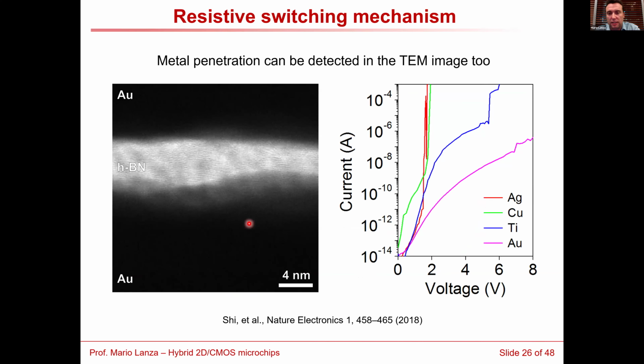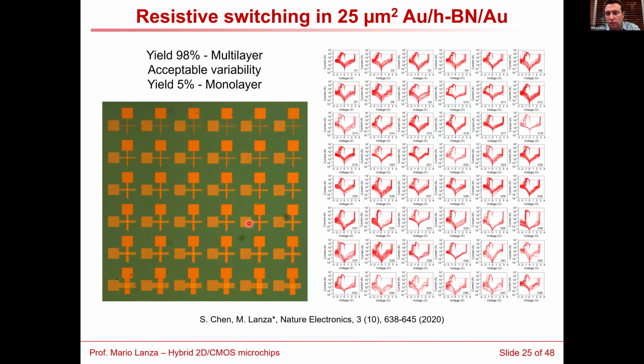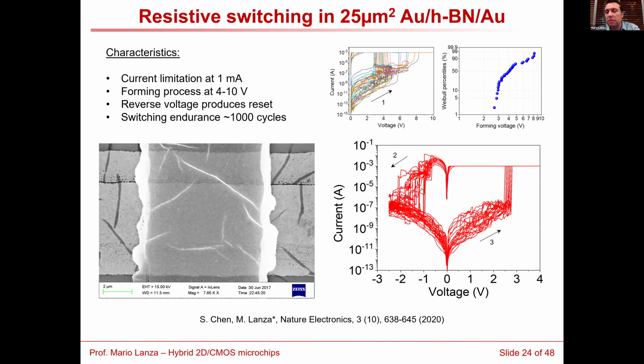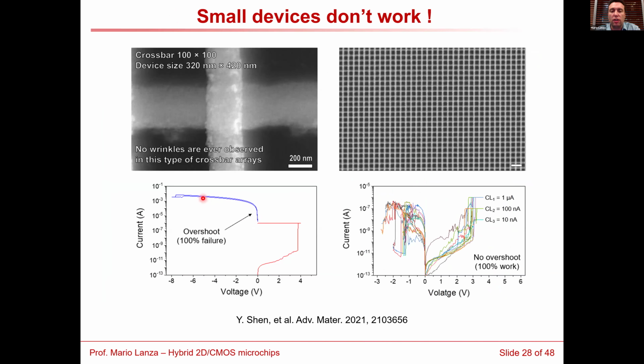For the big devices, we observe that they increase a little bit, maybe a maximum factor of 10, 1 order of magnitude above the current limitation. But here it is like 3 orders of magnitude, okay? So after that, we observe that there is no resetting, okay? There is no reset. And this is something that shocked us because it happens randomly in around 50% of the devices. And then we were a little bit confused, like why does this happen?